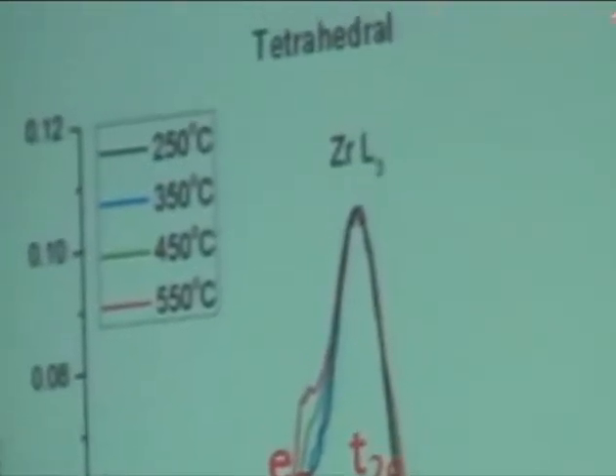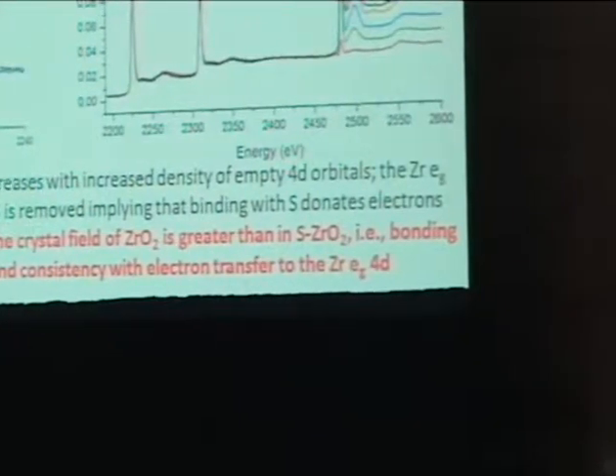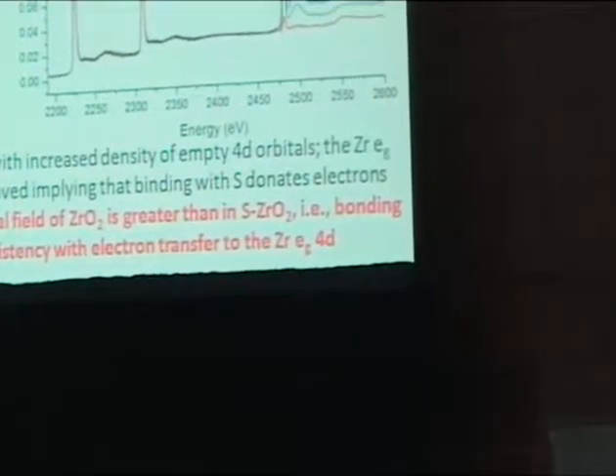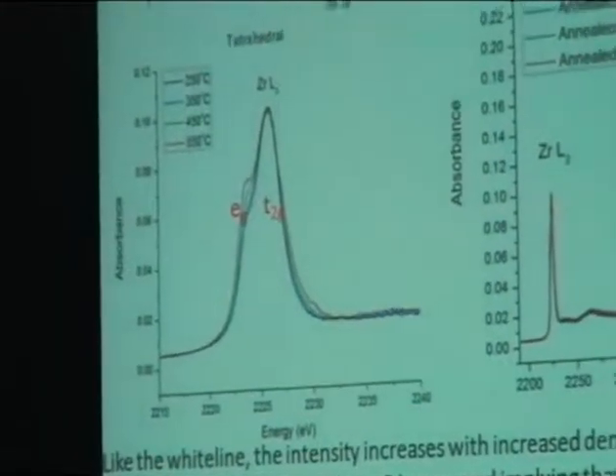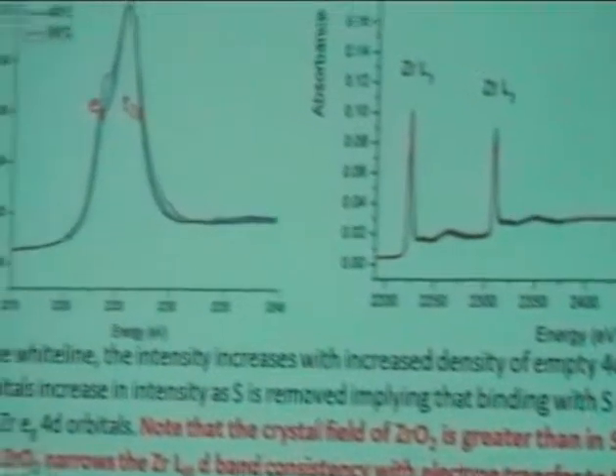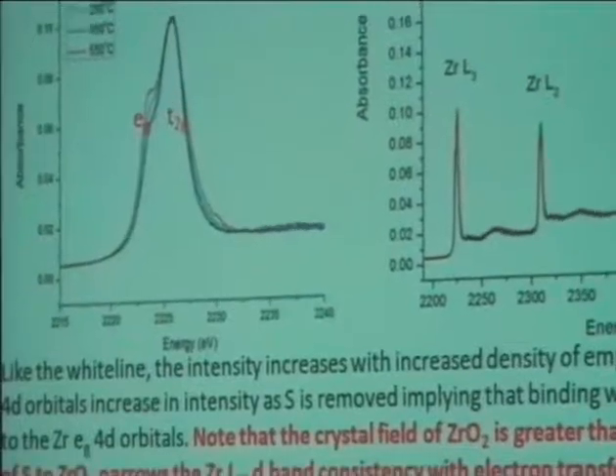And what you see is we're removing the sulfur, 250 to 550. As we do that, the intensity goes down. That tells us that the electron sharing is with the lower energy. That's what we expect. But it tells us a couple other things. If you look closely, you'll see that when the sulfur is on the surface, we have a narrow peak. And when we remove the sulfur, which is the red one, the width increased. That means that the sulfur is changing the crystal field. That is, the crystal field splitting is smaller in the presence of the sulfur, meaning we have a narrower peak. And in the absence of sulfur, the splitting is greater.